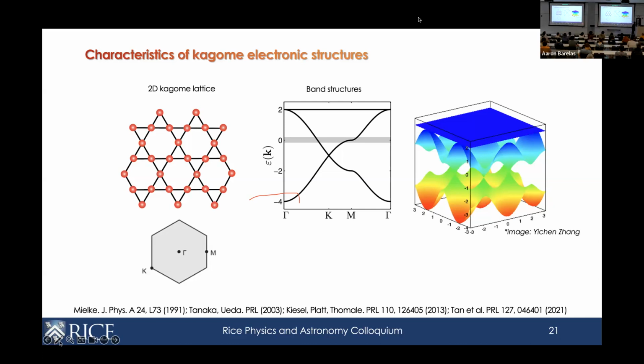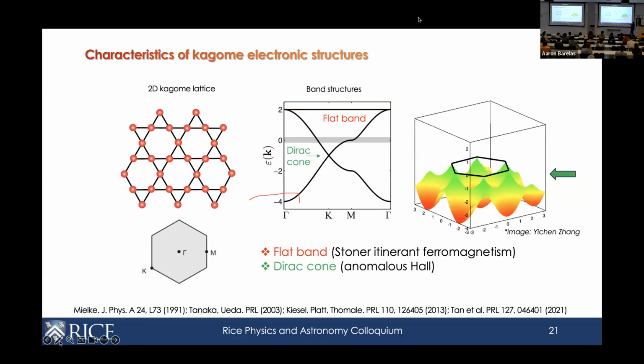This is the real 3-dimensional band structure, and the 3 key signatures are the following. First of all, we have the flat band, which you can see here. This is the flat band, which is flat everywhere in momentum space. And if you tune your chemical potential close to this flat band, then there is a Stoner instability that will lead to itinerant ferromagnetism, at least according to the theory. Second is that there's always a band crossing here at the K point, right? This is the K point in the Brillouin zone. And so just 2 bands crossing without opening any gap. This is called a Dirac cone. And if you tune your Fermi level to here, and if there's also spin-orbit coupling, that will actually give you finite Berry curvature and give you an anomalous Hall effect, but I won't actually talk about this today.